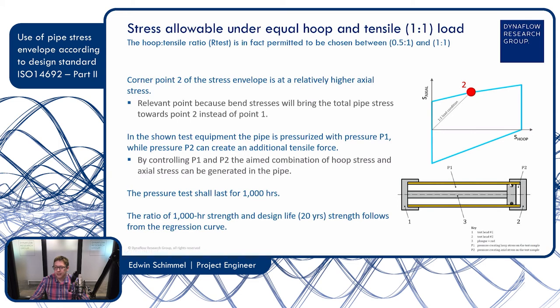So here we have a gasket. And this plunger connects to the end cap here. And what we will do is that we apply a different additional pressure, P2. So we could keep it pressureless here, but we can also apply pressure P2, and that creates an additional axial load on the pipe. So if you pressurize here, we have a load on the plunger, and that will put a force on this end cap, and then a tensile force on the pipe. And then, of course, at the other end cap, you have the same tensile force. So it creates additional tensile force, and by varying the pressure P1 and P2, you can get different ratios of the hoop stress and the axial stress. And we now look at a load condition 1:1, although we can also test for different points.